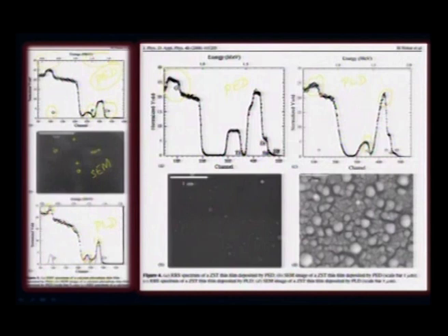As a result, if you look at the SEM micrograph of the PED deposited film here and the SEM micrograph of the PLD deposited film, you can see how the grain structure differs. In other words, this surface seems to be relatively much finer and smoother than the discontinuous grain growth in the PLD structure. Therefore, there are a lot of advantages when we specially play around with complex materials.